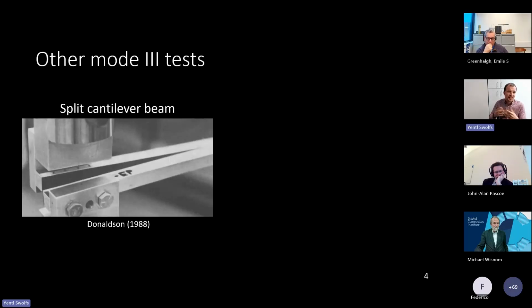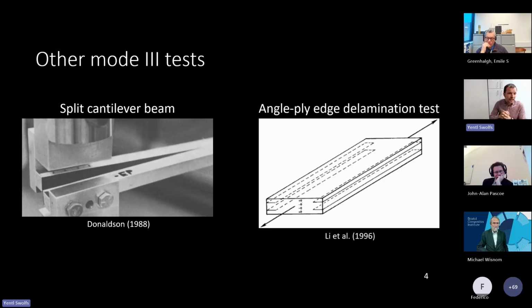So there have been other tests that have been developed, like the split cantilever beam. You can see this as a double cantilever beam, but then just loading it in the other orientation, and you can see that illustrated quite nicely on the image. Another approach is to use an angle ply laminate, apply a delamination along both of the edges, and then simply put it in tension, and then you'll also get mode 3 dominated crack growth, and you can study how the delamination grows in that particular loading scenario.